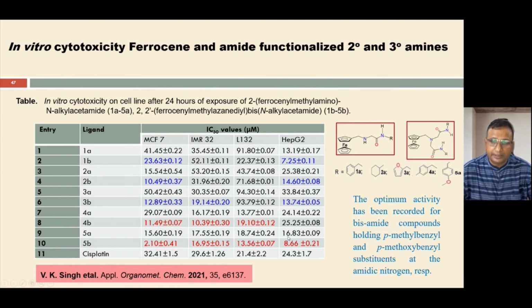All the ligand precursors, secondary amines as well as tertiary amines, have been screened for their potential anti-cancer activity against a wide range of cell lines: breast cell lines, neuroblastoma cell line, liver cell line HepG2, and the data is summarized in this table. As you can see, in general, the activity of tertiary amines is found to be superior to the secondary amines. That may probably be due to the increased number of biologically relevant groups, amide groups, in the tertiary amines, and in particular the anti-cancer activity of compounds 4B and 5B.